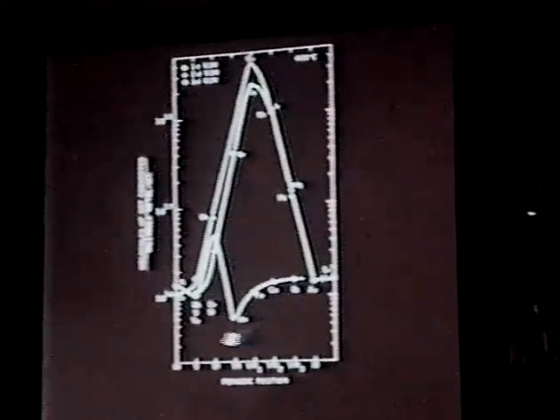But you need to keep in mind that there's another aspect there, the selectivity in relation to structure. In any case, as I said before, the stable states, though they have very different structures, will give these very smooth periodic effects, which just show you the ability of these catalysts to do the reaction I just showed you, as a function of periodic position.